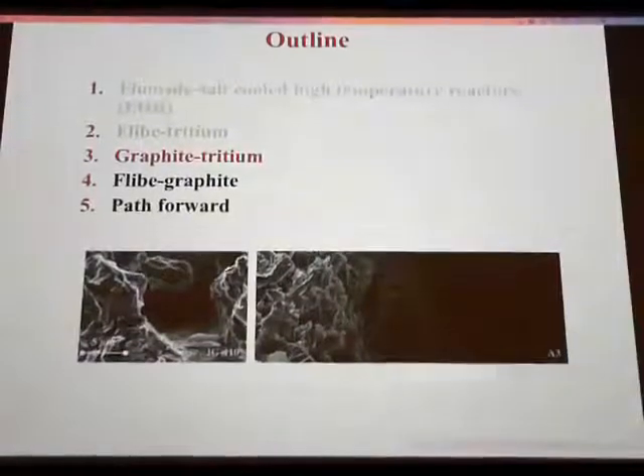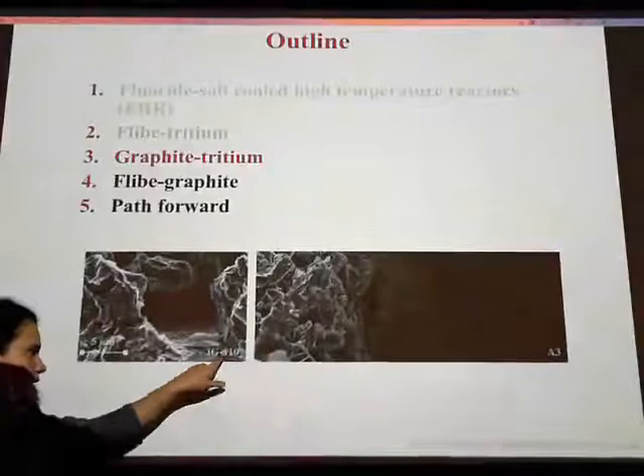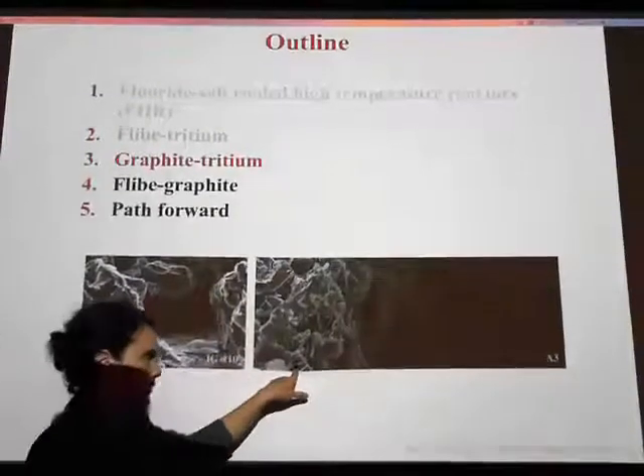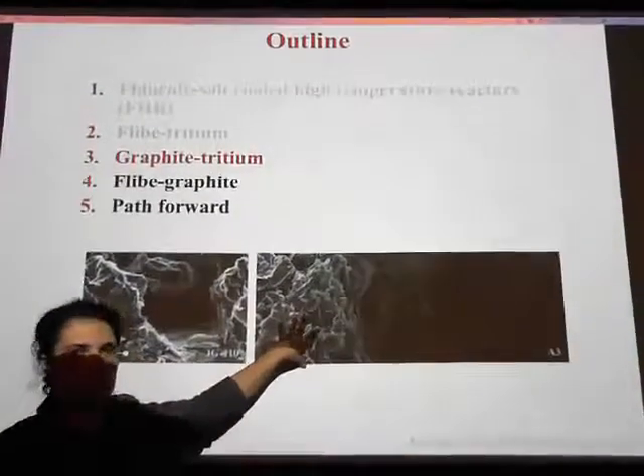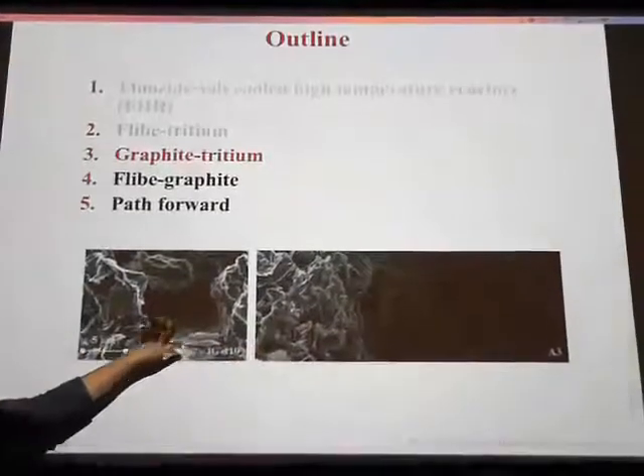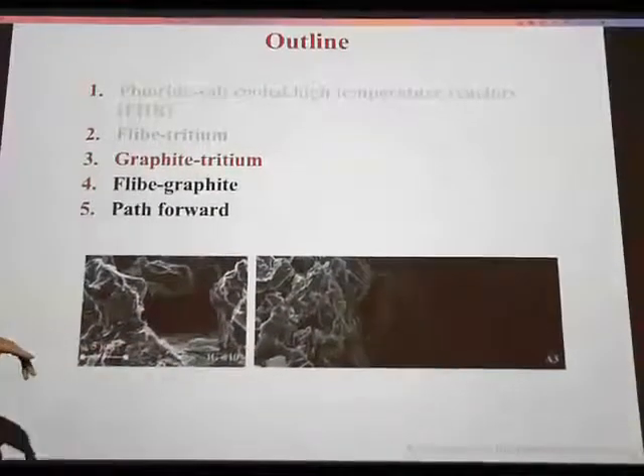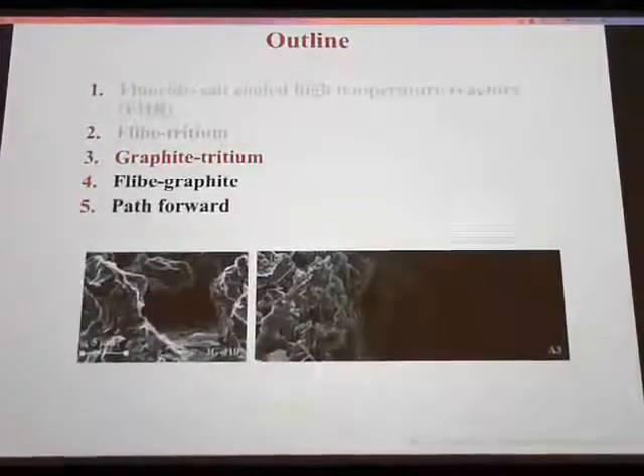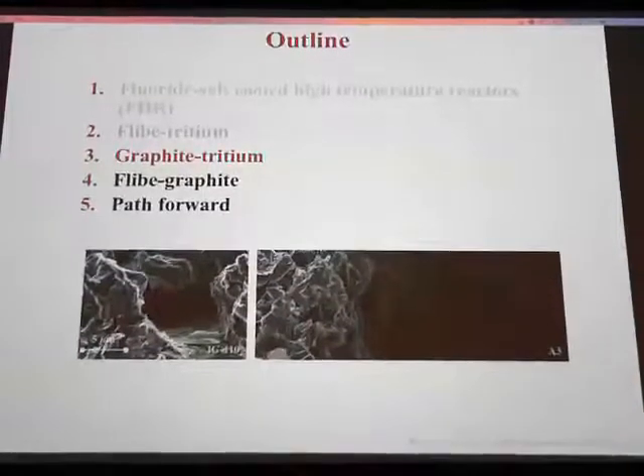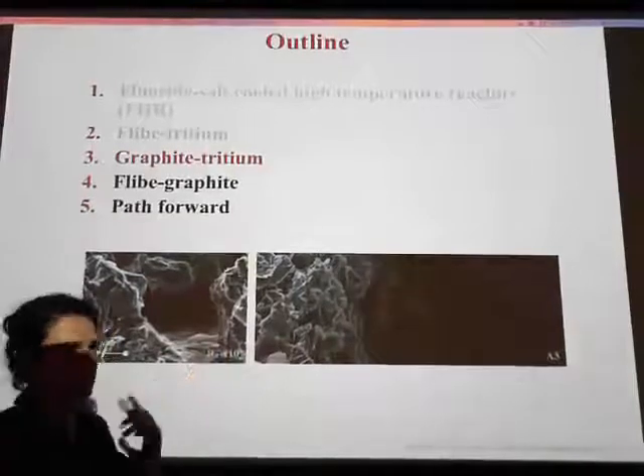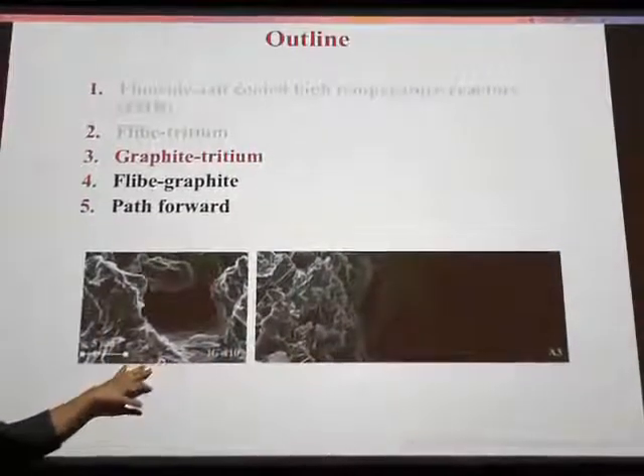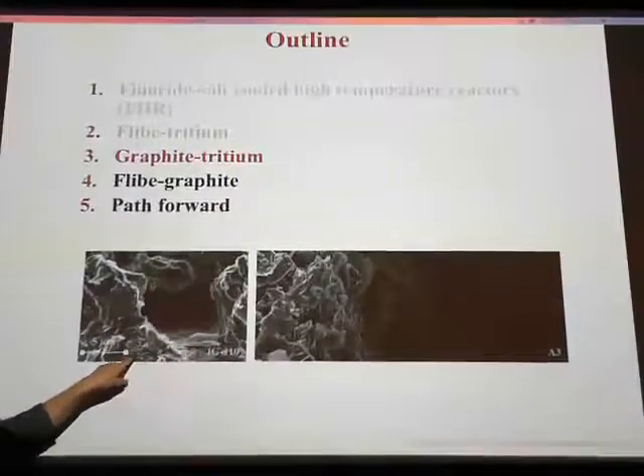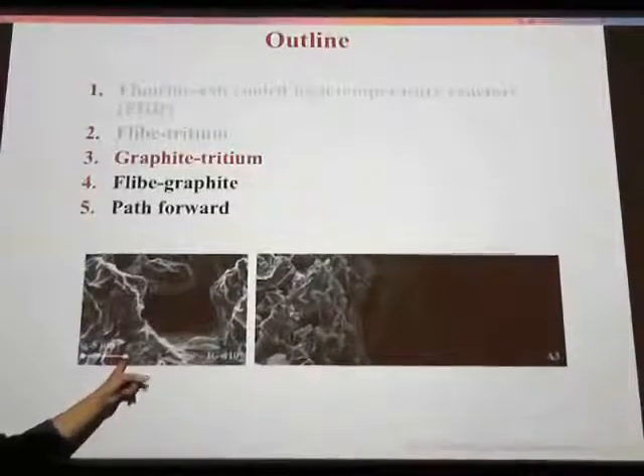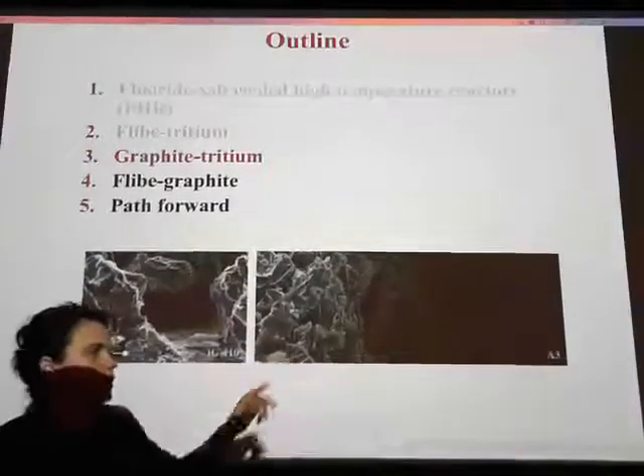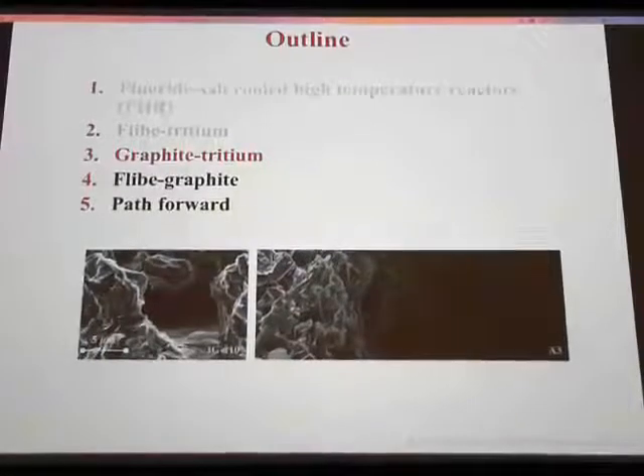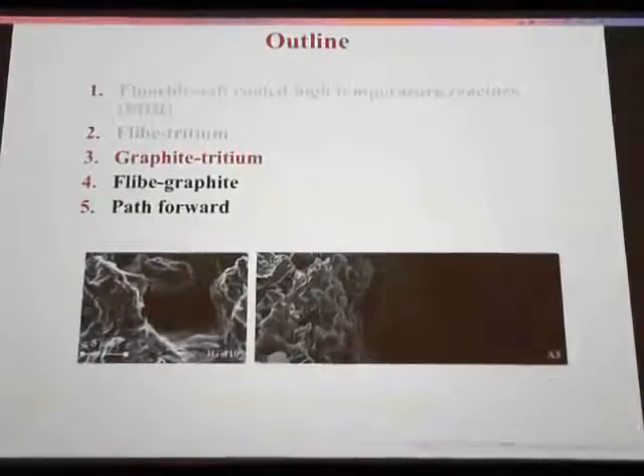And so what you see here are 2 types of graphite. This is nuclear grade graphite, this is matrix graphite. This is what's in the fuel, the removable fuel elements. This is what's in the reflector blocks, and also possibly in some of the pebbles, because you have a pebble bed. And you could put fuel, but you could also put pebbles of other materials. And most of the data that exists in the literature is from nuclear grade graphite. Matrix graphite hasn't been well characterized, primarily because it's scarce. Not a lot of people manufacture it.